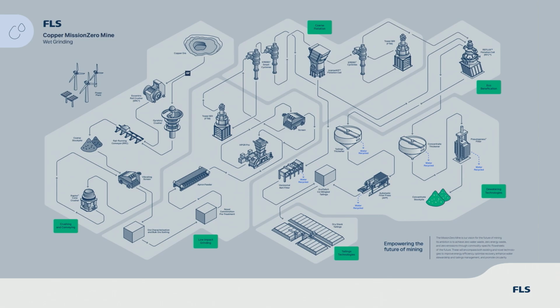So really what we're trying to do here is make the large portion of our material being rejected go into a horizontal belt filter instead of pressure filter filtration, to ease the dry stacking areas. And then with the fine flotation, we had to go through a regrind, and then we had a standard thickener filtration. And we mixed the fine tailings with the coarse tailings to produce a more stable geotechnical stack.